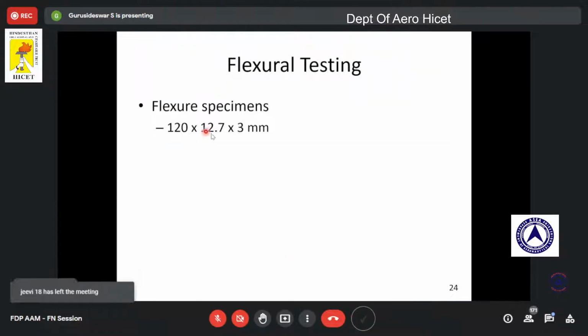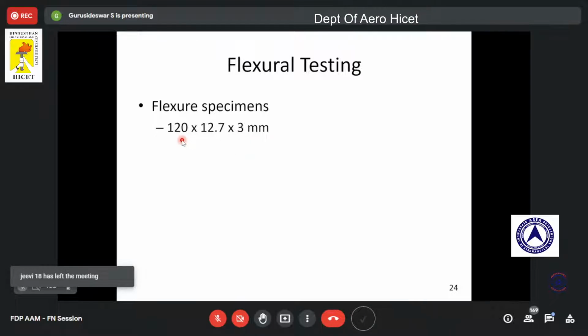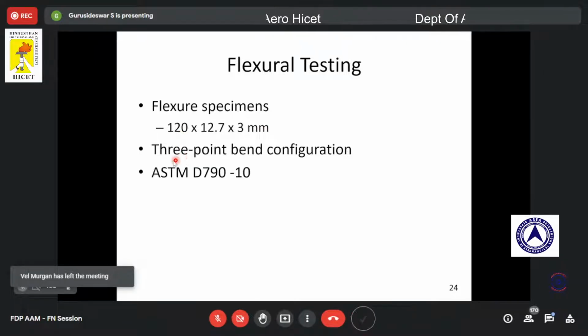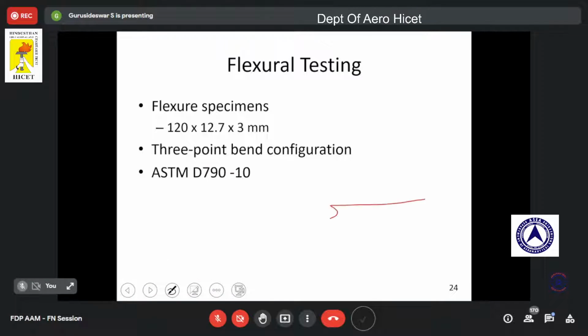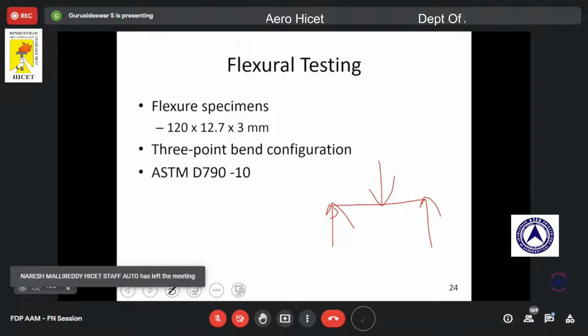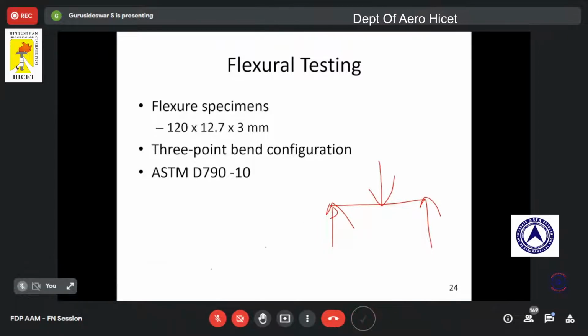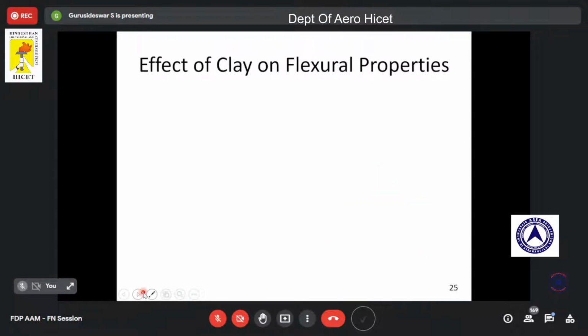And then for structural testing, again we used small beam samples as per ASTM D790, and we used a 3-point bending configuration. So you all know the 3-point bending configuration. It is supported on two supports, and the loading acts at the middle of the beam. So this is a typical 3-point bending configuration.